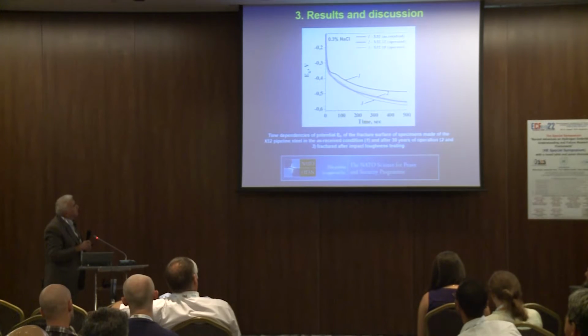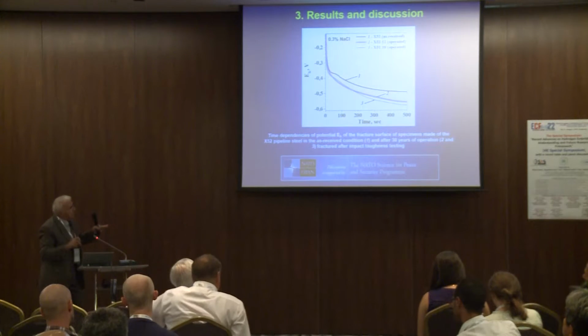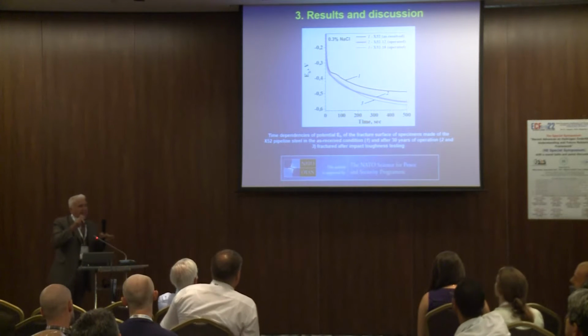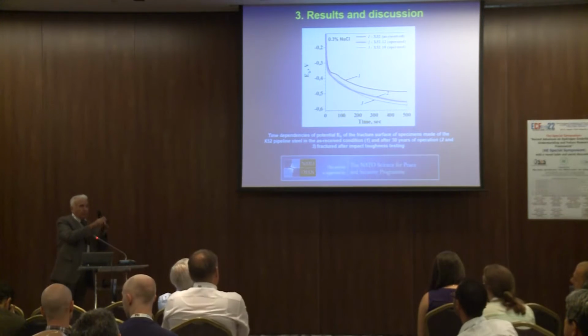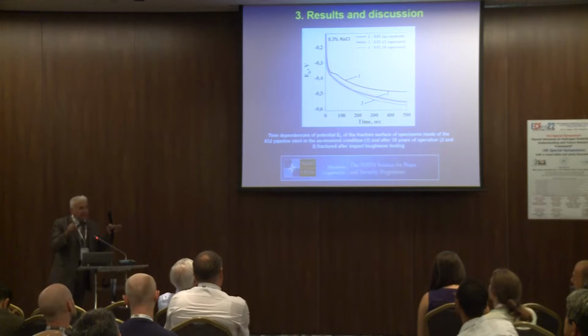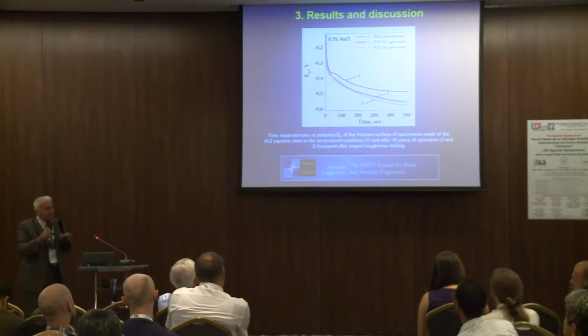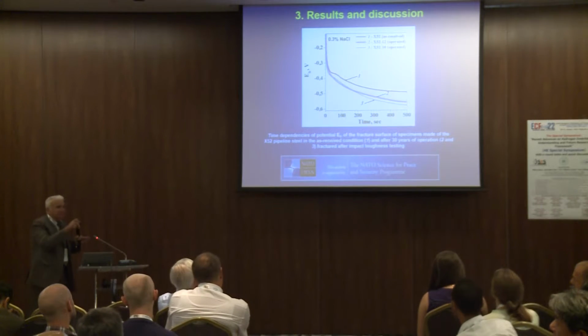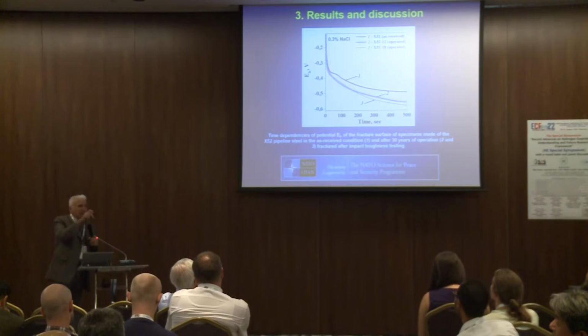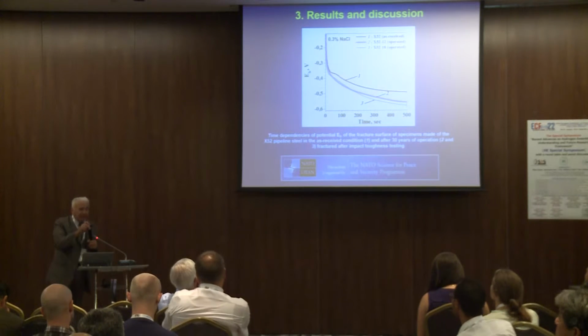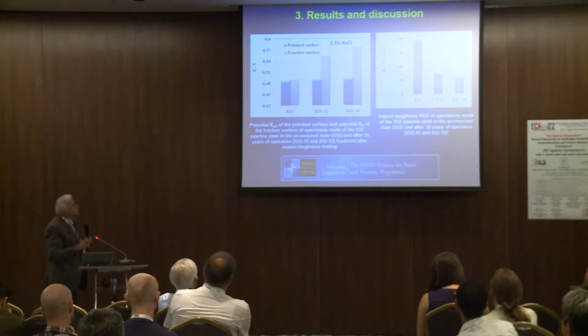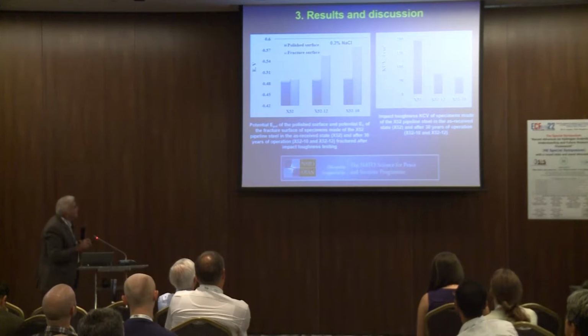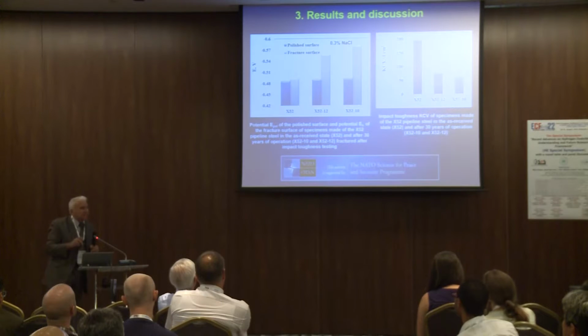So we measure and compare the potential for polished metal, which is usually measured, and for the fracture surface for pipeline steels in the as-received state and after service. And it allows us to build this. There you can see the most important results.